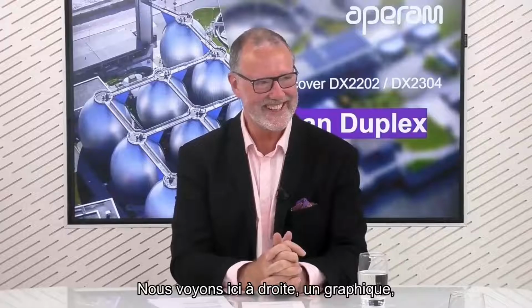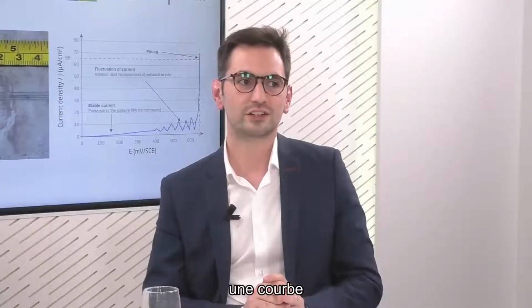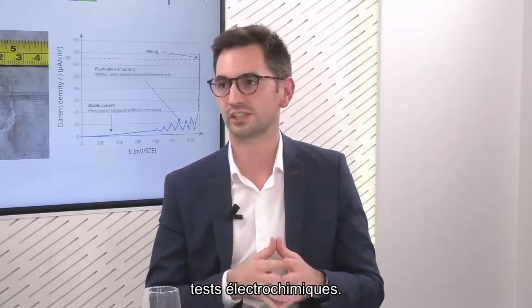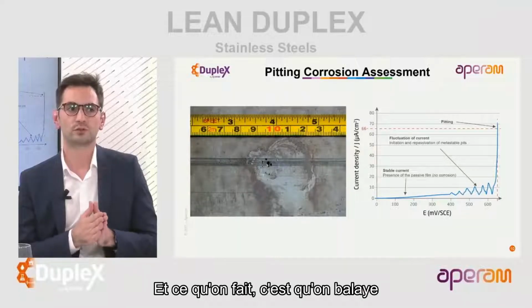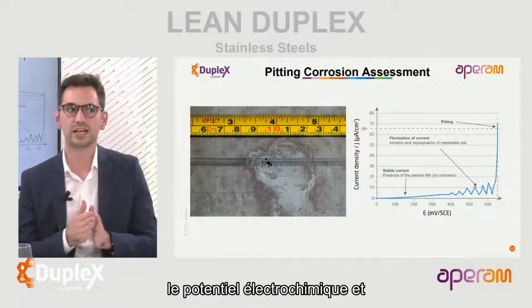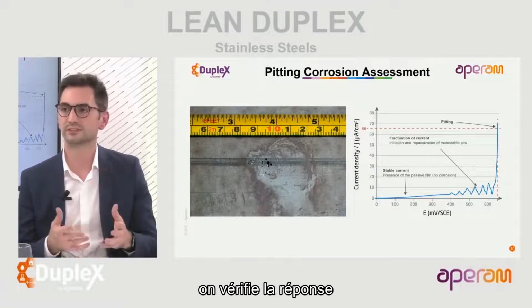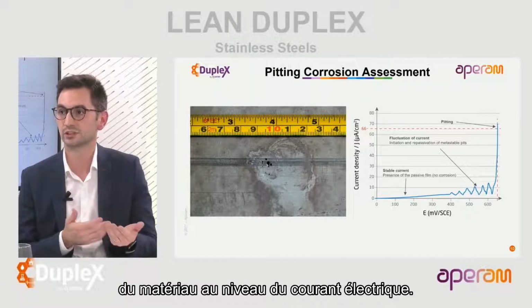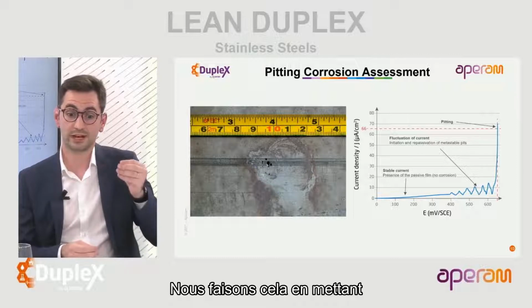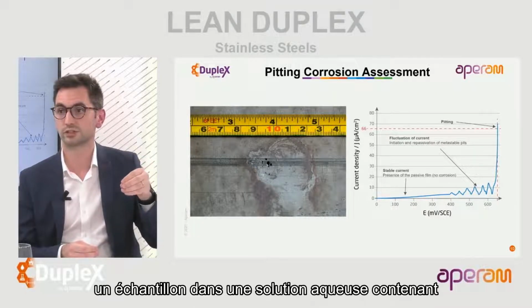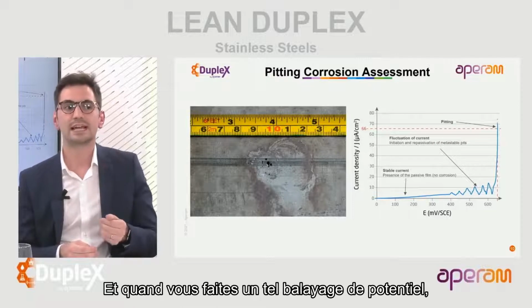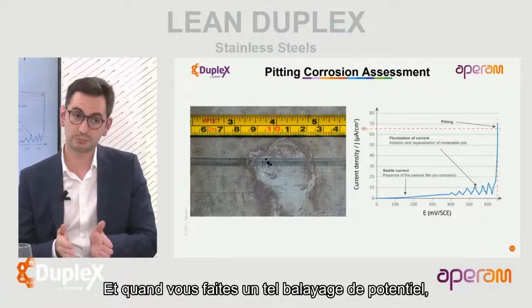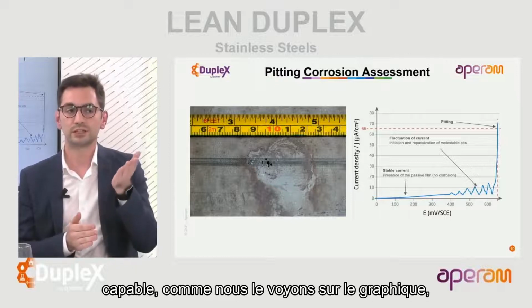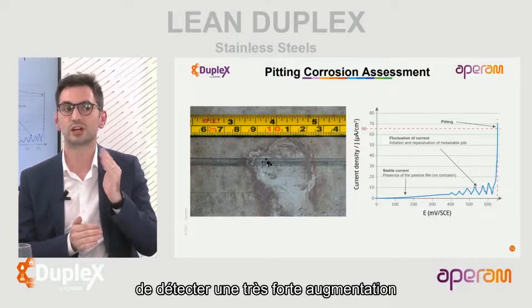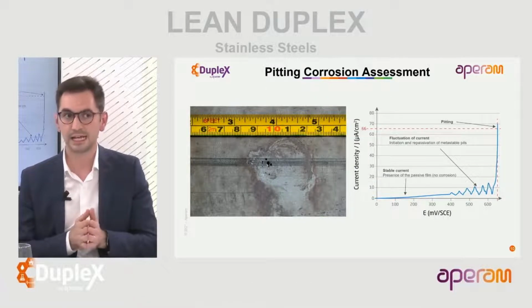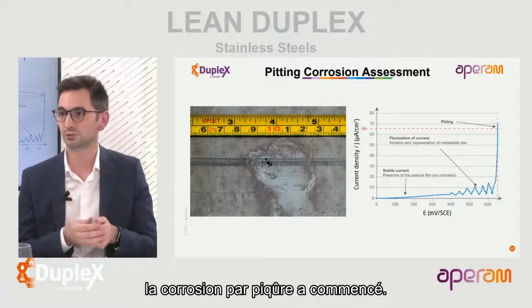We see here on the right a graph, actually a curve, that is the result of such electrochemical tests. What we do is that we sweep the electrochemical potential and we check the response of the material in terms of electrical current. We do that by putting a sample inside a water solution containing chloride, so seawater. And when you do such a potential sweep, at some point you will be able, just like we see on the graph, to detect a very sharp increase of the electrical current. And when you have that, it means that the pitting corrosion initiated.